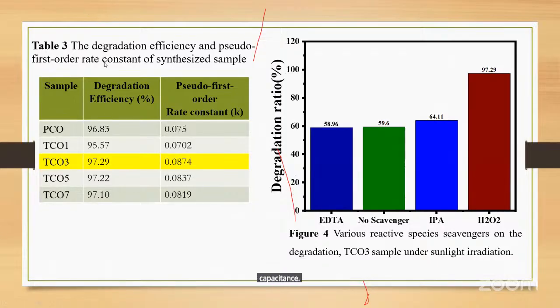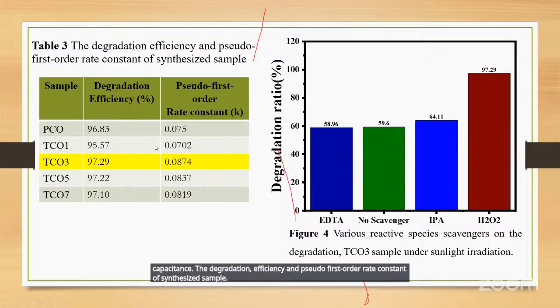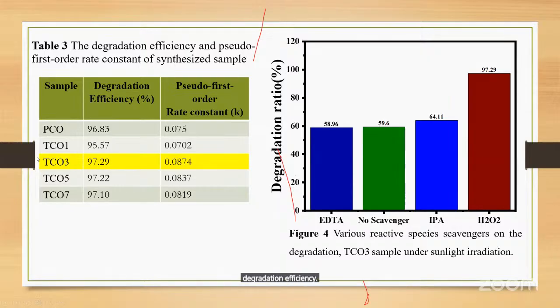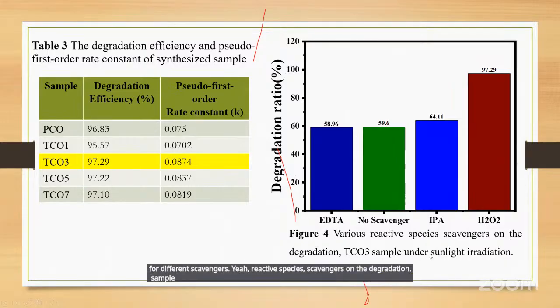The degradation efficiency and pseudo first order rate constant of the synthesized samples. Degradation efficiency, this one, and pseudo first order rate constant is 0.0874. Degradation ratio of this, you see, H2O2 for different scavengers, reactive species scavengers on the degradation of the sample under sunlight irradiation.